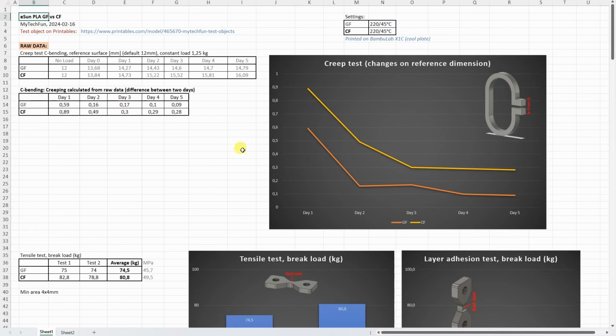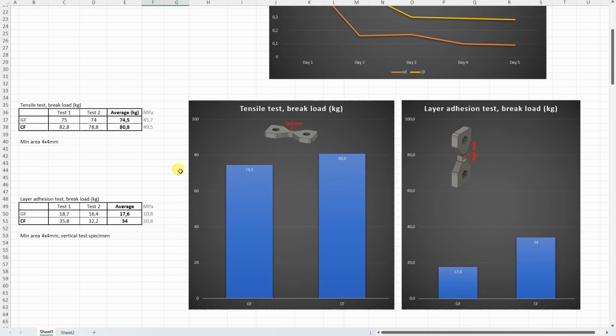Let's analyze the results in this Excel table, which you can download from the mytechfun.com website. And let's analyze the creep test, and I can see that the glass fiber had less deformation, but here the creeping is more important. So the difference between 2 days we can see on this table or on this graph, and even in this case we can see that the glass fiber filament creeps less compared to the carbon fiber version.